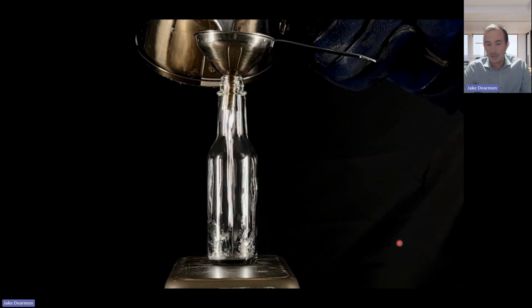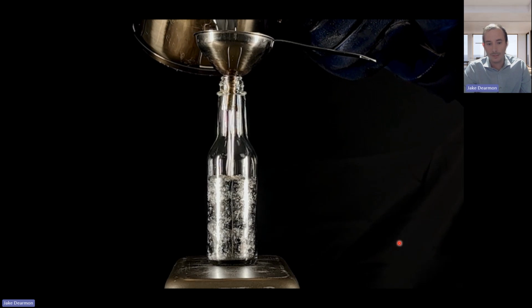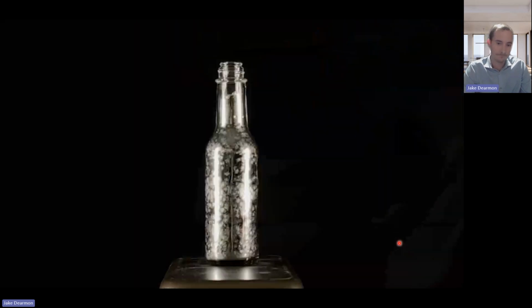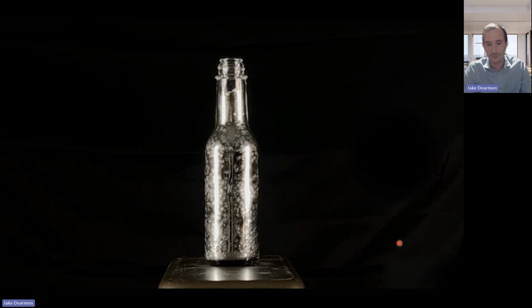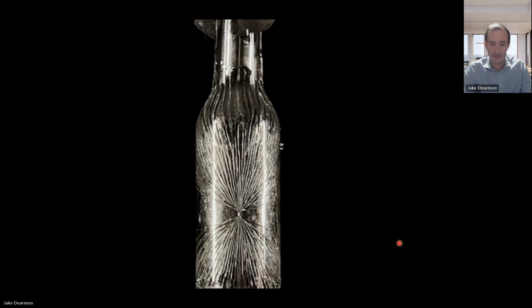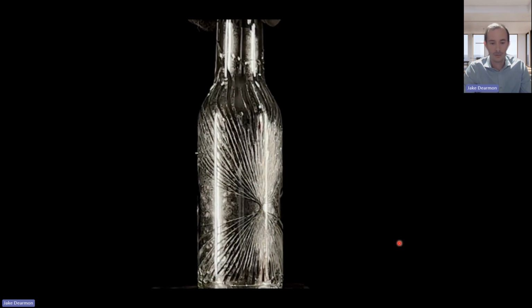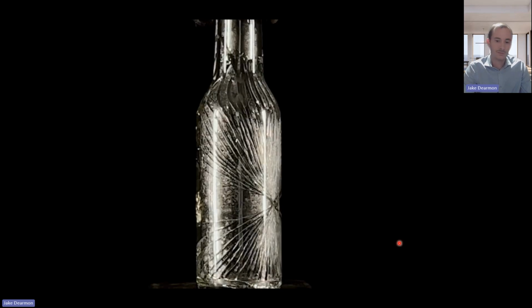So in this video, we'll see we're actually pouring liquid alloy into a bottle here. It's a glass bottle. And after it's full and we fast forward a little bit, we see that cracking. And that cracking is actually the volumetric expansion of that alloy. It's inducing hoop stress around that bottle. And it's actually that force of expansion that's cracking that glass bottle. Now, obviously, downhole, we're not trying to crack casing, but there's a lot of metallurgical differences between the glass and casing, but that's showing some of that volumetric expansion in that glass bottle.